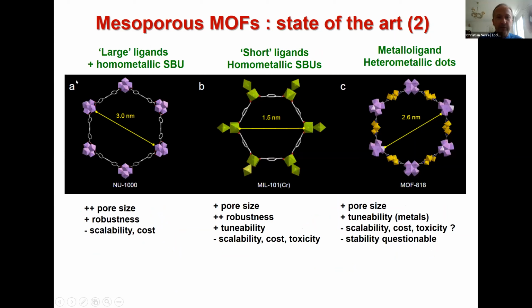These are three representative benchmark mesoporous MOF materials. Like NU-1000, with a large ligand and a single SBU, it is very interesting, but it is hardly scalable and probably costly. If you use MIL-101, then in this case the metal is cheap, it's chromium, so it's not too expensive, it is very robust, it can be tuned by the ligand, but then there is the problem of the chromium with the toxicity and so on. And then I like this last approach. This is a heterometallic construction of mesoporous MOF, and you take copper and zirconium and you form this heterometallic structure, and then it allows you to not only change the pore size, but to change the metals.